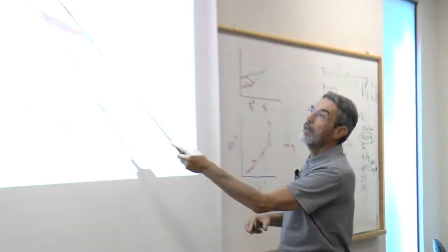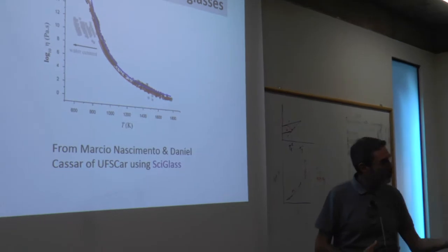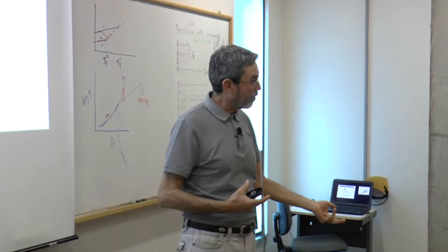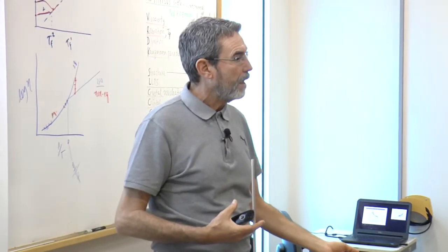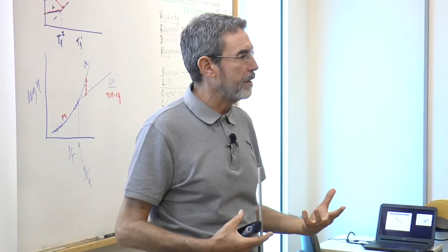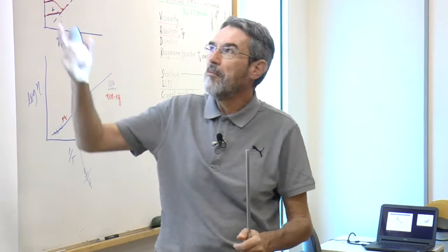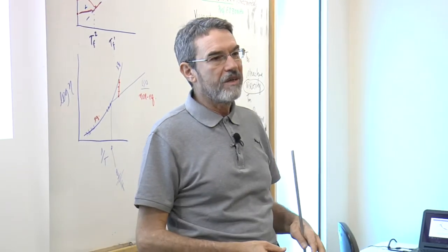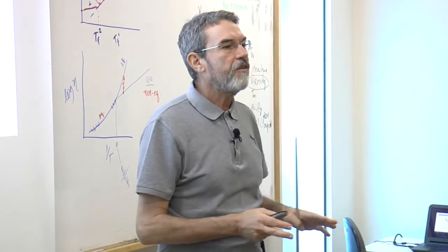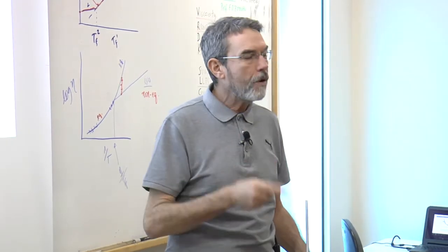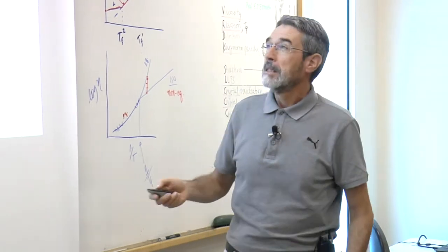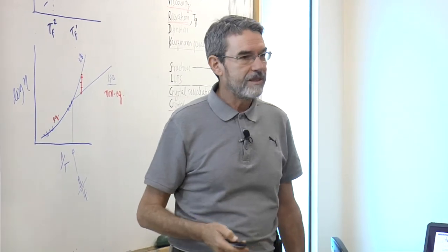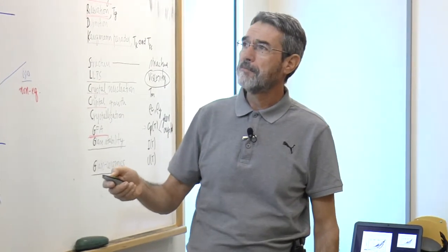Different regarding dynamic properties, viscous flow, diffusion, nucleation rates, crystal growth rates. It doesn't have a large effect on mechanical properties. If you're going to measure the mechanical properties, a little bit more or less of water makes no difference. Or the density of the glass, or even the refractive index, these differences are negligible. But for dynamic properties, this is very important. I'm saying this because not many people realize that glasses have water and how important this component is.